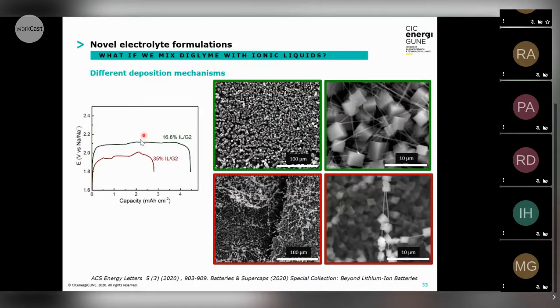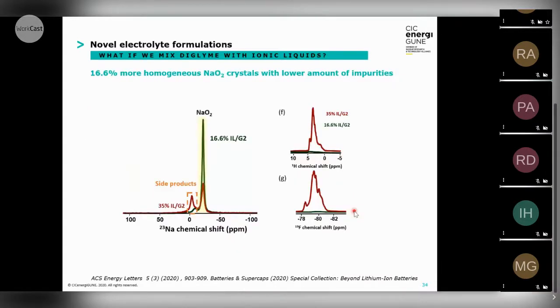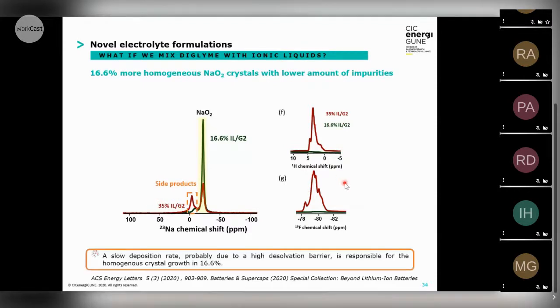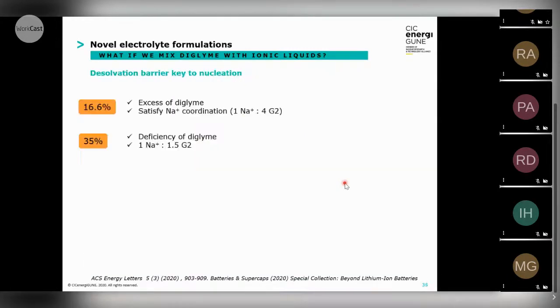Here you can see we also did 2 concentrations in order to get an insight into the solvation. We can see that in the case of the lower concentration, you get bigger cubes, and in the case of the higher concentration, you get smaller cubes. And we will explain why this is. First, one next thing about this electrolyte solution is that in the case of the 16.6% mole sample, even the SEI reactions are really low. If you go to higher salt concentration, you start to see these SEI reactions.